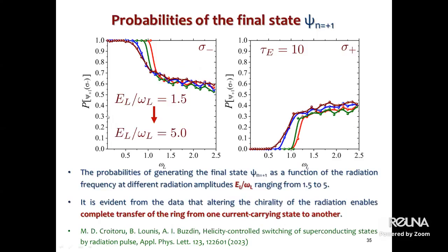This figure presents the probability of generating the final state +1 as a function of radiation frequency at different radiation amplitudes, ranging from 1.5 to 5. So red corresponds to 1.5, brown to 5. The external radiation pulse was approximately 10 in Ginzburg-Landau time. Sigma minus polarization is for the left panel, sigma plus polarization for the right panel.